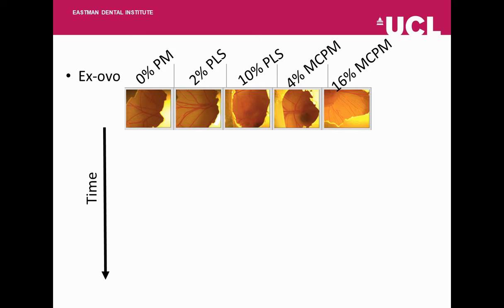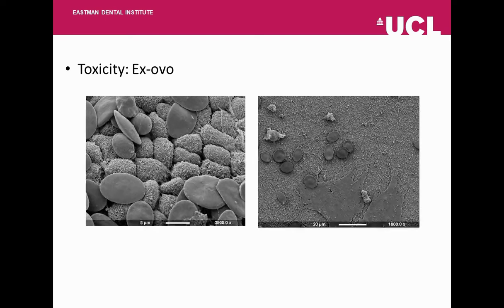Over time, I assessed how the chick embryos developed, and finally at day 14, when I collected the graft, the membrane was attached to the disc, so it shows the disc created an environment where the membrane of the chick embryo was happy. And I took some images on a scanning electron micrograph for these, and we can see red blood cells, we can see cells. So this is a pilot study as well, so we need to assess this further and see what we're seeing, why we're seeing what we're seeing.